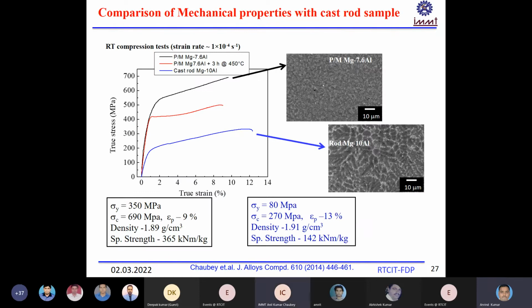So here you can see the final mechanical property. We have compared the mechanical property of this cast structure with the powder metallurgy structures. You can see this is the mechanical property in tensile. This is of this magnesium 10 aluminum cast structure, where this gamma phase are along the grain boundary, and this is the mechanical property of this powder metallurgy structure, where you can get around 3 times. Here is 700, here you are around 200 megapascal, and the ductility almost remains the same.